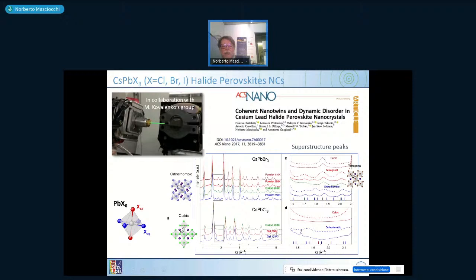Gel means a wet powder, so a not completely dry system. As you can see, the traces are nearly similar, but there is a portion of the spectrum which is very different. The major difference occurs in this section, where this Q angle is still at the translation of the real angle, and this angle is near 5 degrees. So there are several peaks, which we call superstructure peaks, which arise from the different symmetries here.